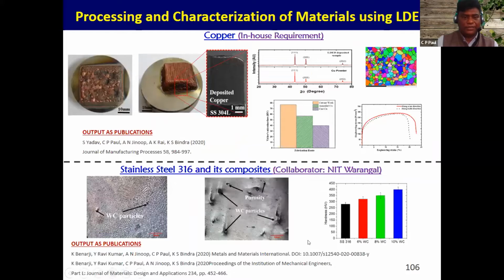When you talk of copper, we did some experiments. We tried to identify the gaps and work on them, and got very good deposition. We collaborated with NIT Warangal to build some components, some SS tungsten carbide composites. A big change we got, and we deposited. And you see how the hardness increased with the inclusion of tungsten carbide. It's a beautiful example of how a different material can be built using additive manufacturing technology.